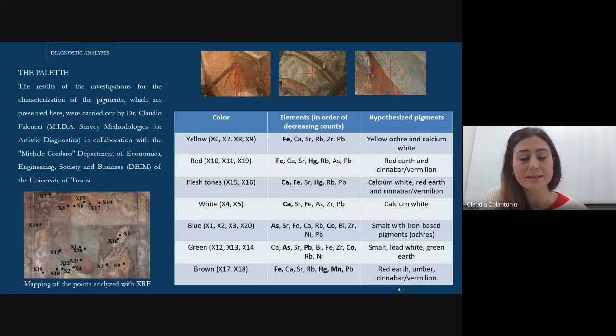As regarding the painting technique, it is a mixed one, partly a secco, partly in fresco. According to XRF analysis done in 20 points on the artwork surface, it was possible to detect the joint presence of calcium, iron, rubidium, strontium and zirconium, attributable to the constituent materials of the lime-based mortar and to a material of volcanic origin similar to pozzolana. Concerning the pigments, the presence of iron in the reds and yellows can be referred to the use of ochres, and the cobalt in the blue to the use of smalt. Lead was also detected in all points in low counts and in higher quantities in white-coloured areas. Mercury was also detected in some red spots attributable to the use of cinnabar vermilion.